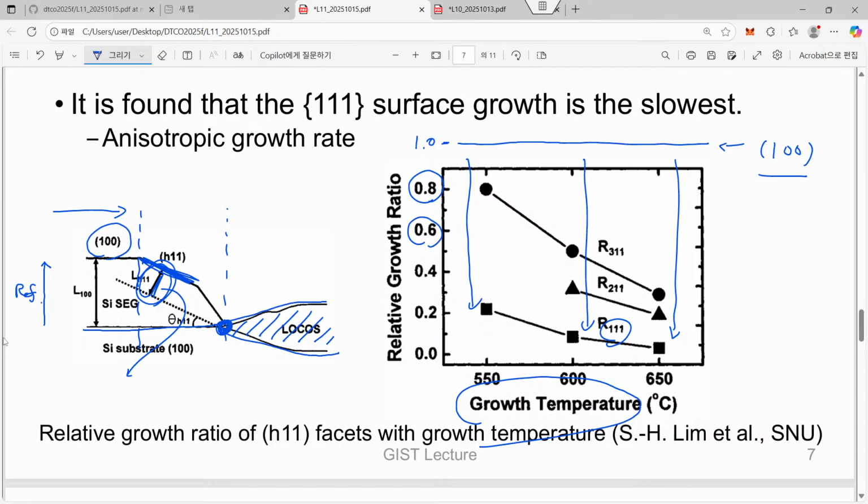But please think about this one. When we have, for example, a certain circular shape as an initial one, it can contain a lot of different surfaces. And let's say that for a certain direction, for example this direction, we are quite fast. Then we will have a movement of this initial surface that way.